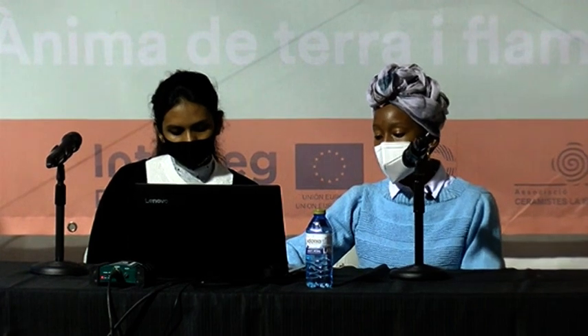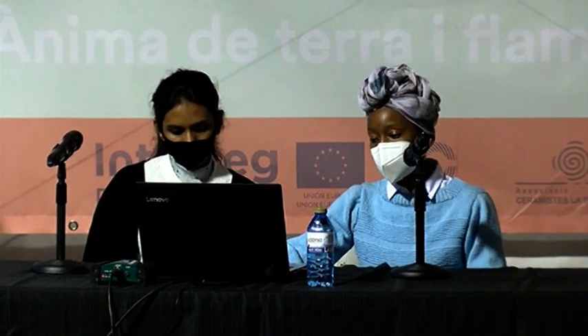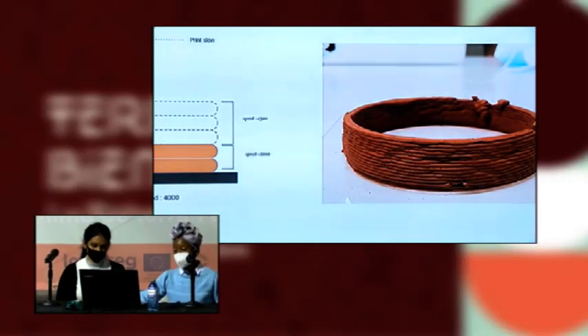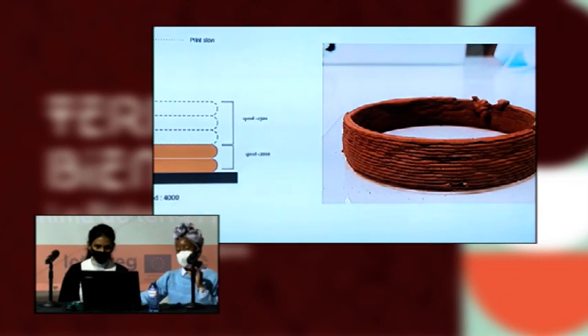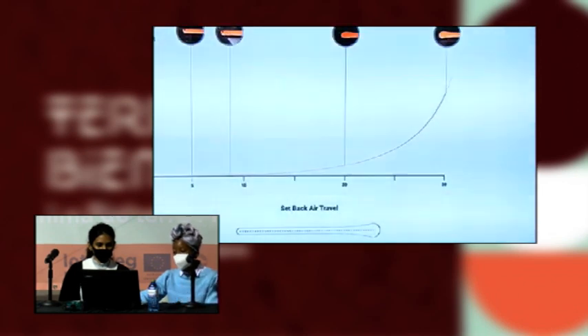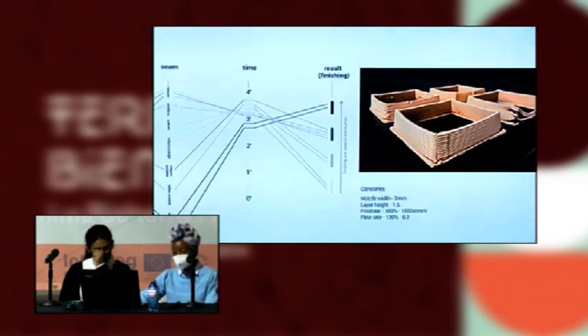How do we understand the machine use and capability? Is through different methods from mixing, machine setup, through to extrusion. We look at 5 different topics, such as machine speed, and we concluded that when you print the first layer slowly, you get a good overall print of the geometry that you're trying to produce. In terms of retraction, in order to get a well-finished product, you need a minimum time of retraction from the start of the print to the end, so the seam is nice and clean.